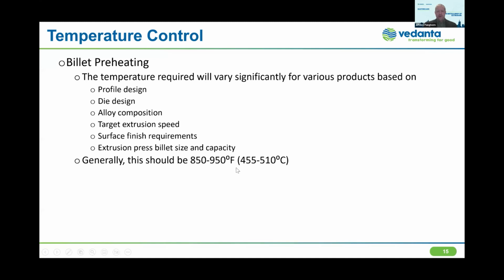One of the more important points, I think, is that we don't want to hang out at the lower end of these temperatures, because we're within, or at least very close to, that critical temperature range. So we want to have a stable operation where we're not just having metal stay at temperature. And we certainly don't want to just leave a preheater on for extended periods of time if we're not producing.